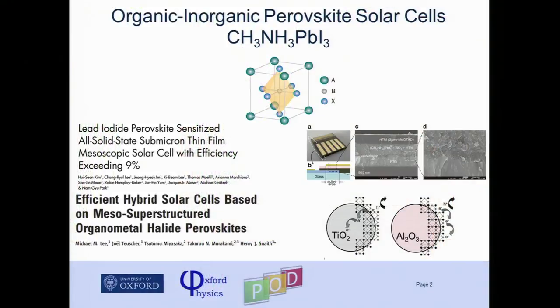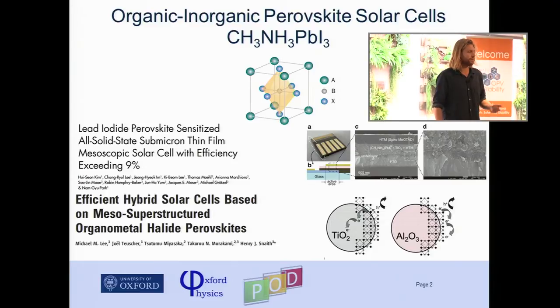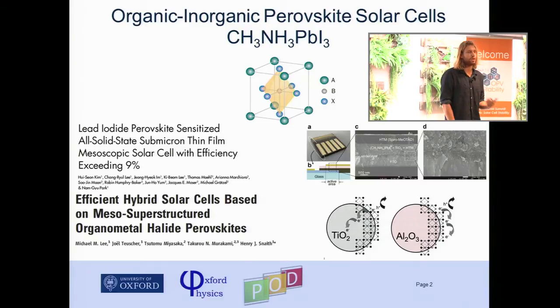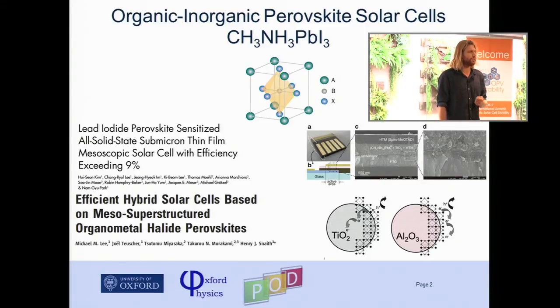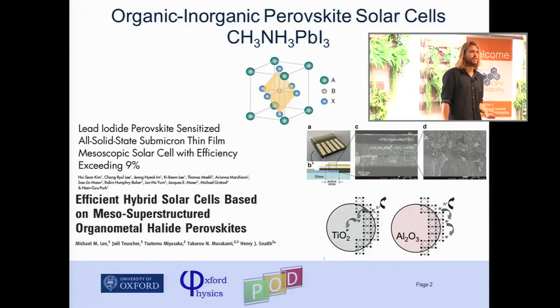I've come second in this session, so I don't have to introduce much about perovskite solar cells. But I would like to say that there are a few fundamental properties of the material that are actually responsible for the quick developments in the field. The first is that the materials are very easily solution processable from commonly available precursors. The second, and probably most important, is that the materials display very long ambipolar diffusion lengths over one micron. This enables them to function in many different types of architectures, including thin film architectures.